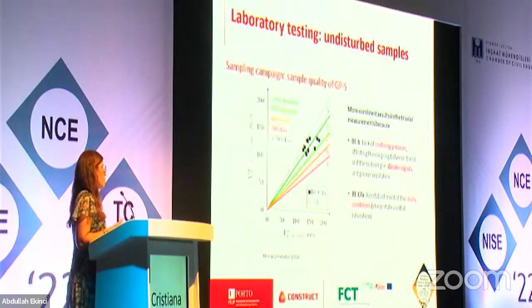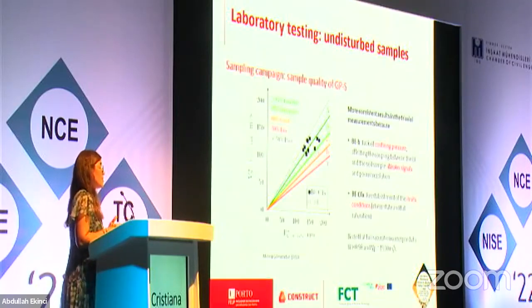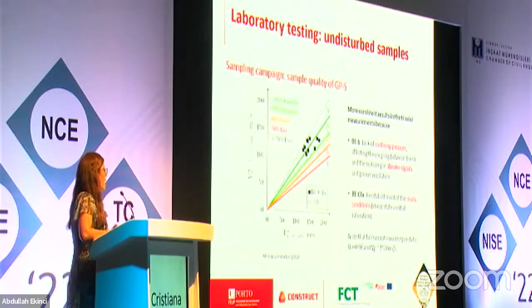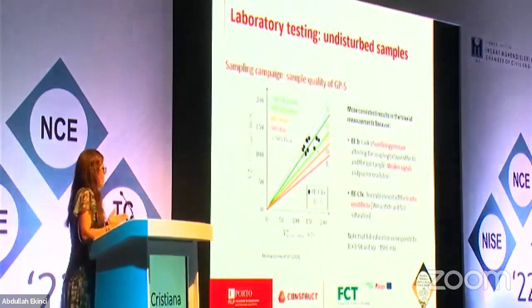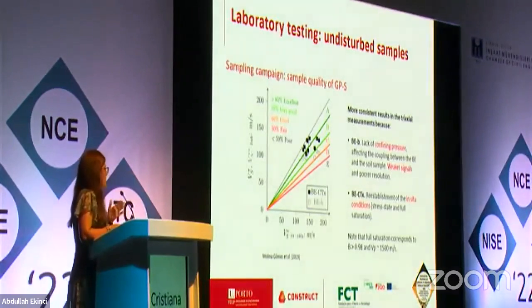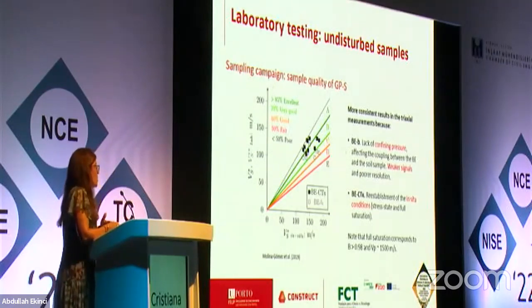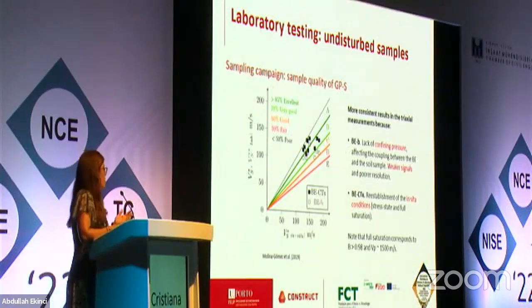And this involves not only the stress conditions, but also the full saturation. And full saturation is very important to us, especially if we're going to do liquefaction analysis. And that process, which I'm not going to discuss here, is only assumed complete when we have a B value above 0.98, and we always measure P wave velocity, and it should be around 1500 meters per second.